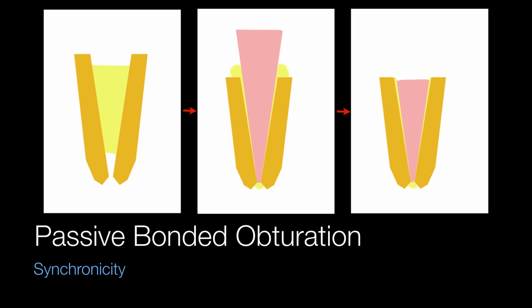root. So this becomes almost like a post-preparation, because let's think about it. A post-preparation and a post-cementation is really the same idea here as hydraulic condensation, where you have one main post, or here one main carrier, and the rest of the obturation is really based on the cement. In this case of a post, it's a resin cement, which would be in the upper half of the root, where it could work because in the upper half of the root you have dental tubules, but in the bottom half of the tooth you really don't have enough dental tubules, which is why resin sealers would not work in the bottom half of the root, which is why bioceramics would be the ideal type of material here.